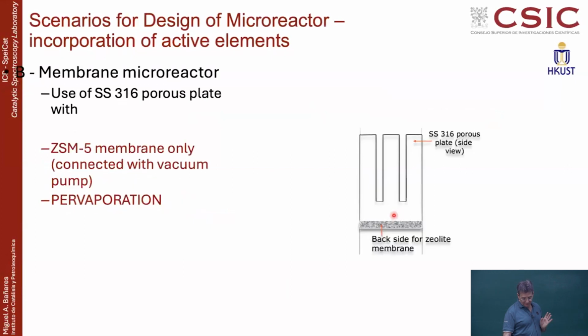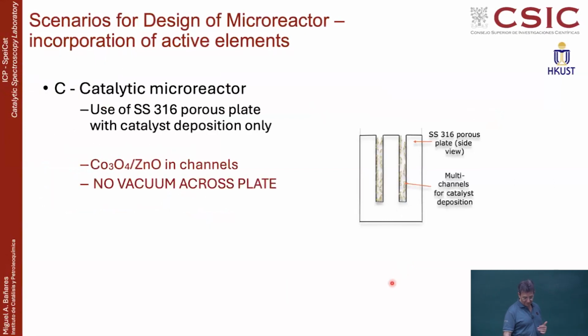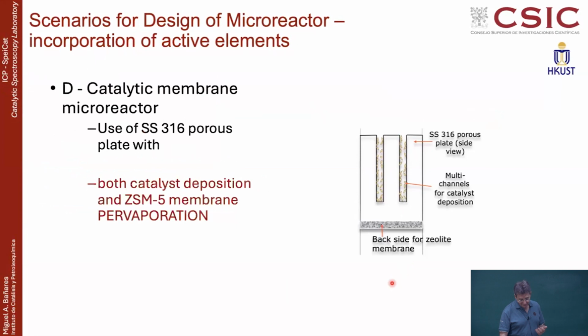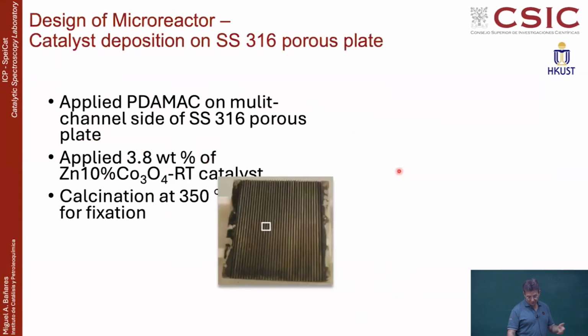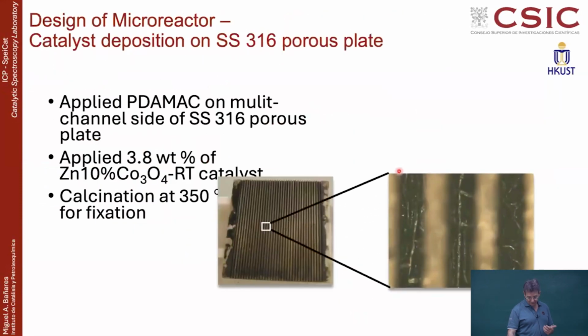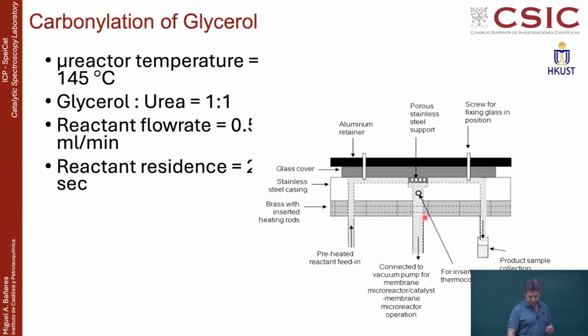So what we do is to put a zeolite, that we grow a zeolite on the surface of it at the bottom. And then inside the channels, what we do is to put a catalyst, this cobalt zinc catalyst that was very good to convert glycerol into glycerol carbonate. And then we put the two things together. You can put a zeolite at the bottom and the catalyst in the channel. So in the end, okay, this is characterization. Inside, you will see that we have the catalyst inside the channel, and then we have a pervaporation unit.